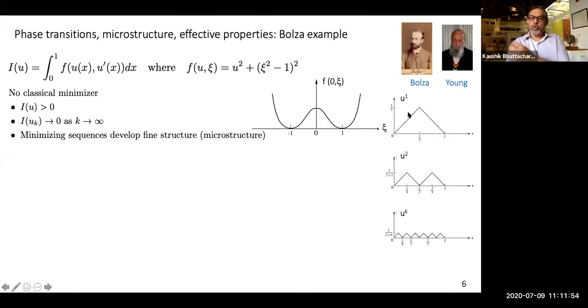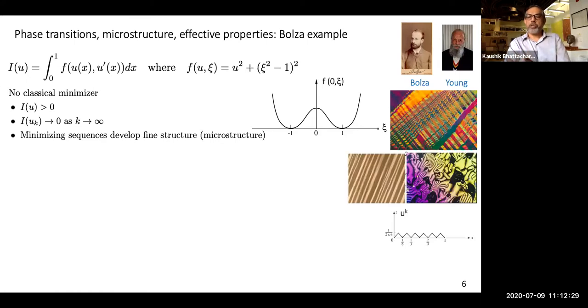However, I can construct a sequence of functions which exploits the fact that the energy is 0 at gradients -1 and 1, but gradually approaches u equals 0 to construct a sequence whose energy goes to 0 in the limit. However, the energy can never be 0, so you really don't have a minimizer in a classical sense. And the reason is that these minimizing sequences develop finer and finer oscillations. And that's a mathematical manifestation of what you see in materials by fine scale microstructure. As you can see in the case of martensitic materials here, liquid crystals here, and liquid crystal elastomers here.